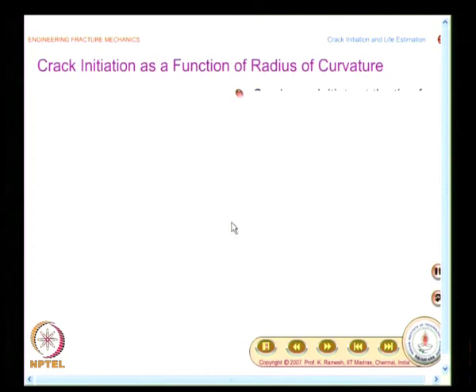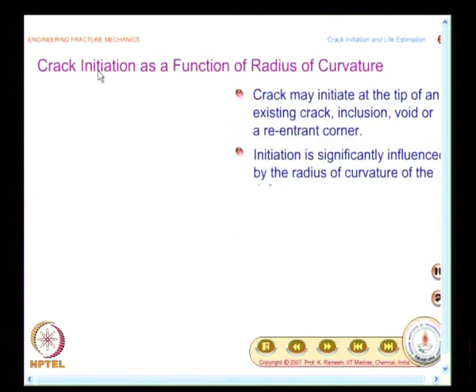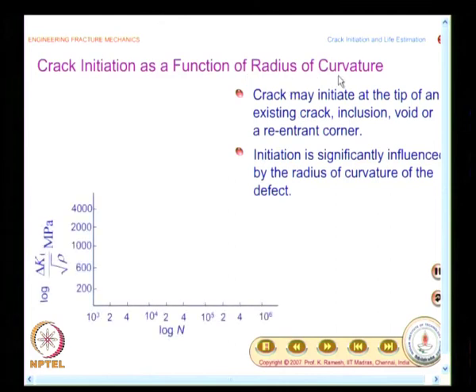See, another important aspect that we have to understand is how a crack initiates. People also have done certain studies on how a crack initiates. We will look at that. And people have looked at crack initiation as a function of radius of curvature. You have a graph drawn. This is between the number of cycles, on a log scale, versus log of delta K 1 divided by square root of rho, where rho is the radius of curvature. This is written in MPa. So, you have 200, 600, 1000, 2000, 4000, etcetera.